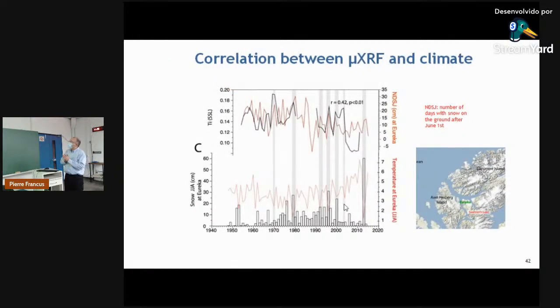Now again, we have a correlation between this micro XRF signal that we measure and the weather station here called Eureka. So Sawtooth Lake is here. It's only 80 kilometers away, and we have a longer instrumental record. So it's a more favorable position here. What we have here is the titanium measured in the varves of the lake, and it is compared with the number of days with snow on the ground after June 1st. And you see we have, again, a nice correlation. And you see that, opposite to Cape Bounty, we have a decrease in the amount of snow, except for this year here. That's the instrumental record at Eureka.